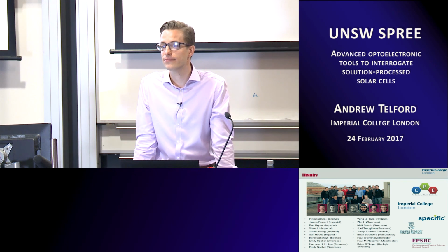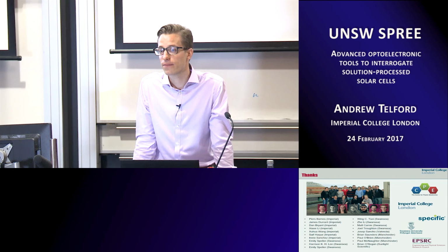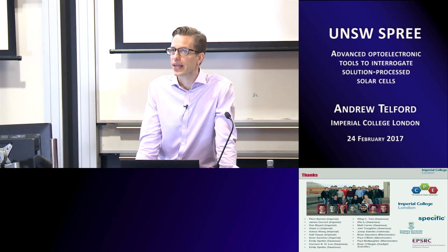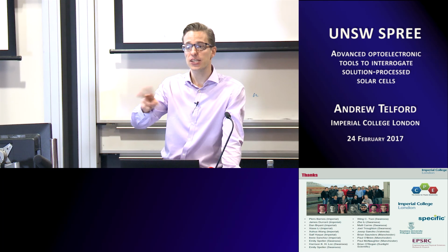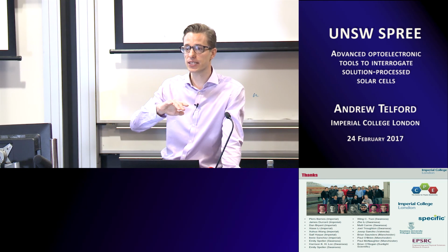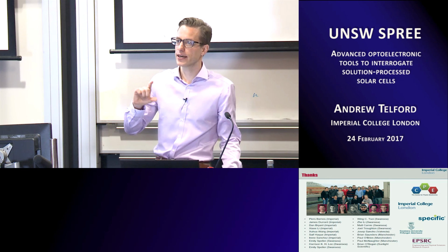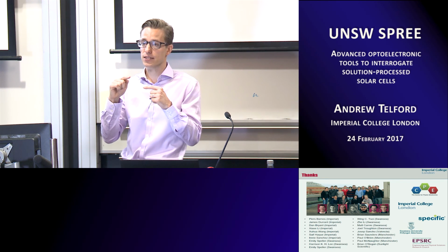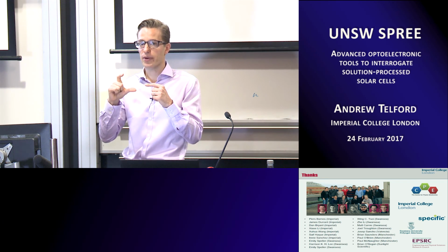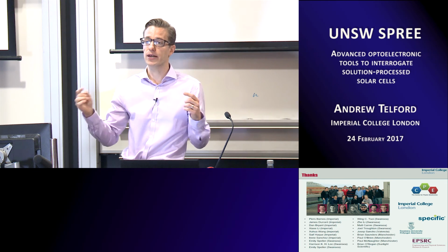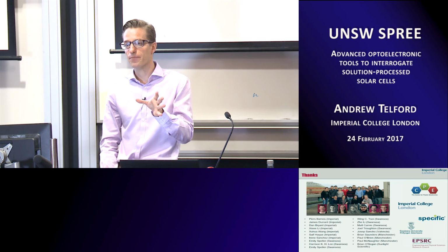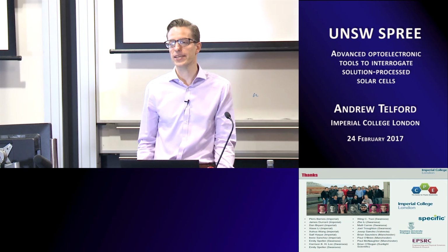You have used the EL to analyze the voltage loss. Can we use PL? The response would be similar. We actually have compared PL and EL, and I do see a similar trend. I think, though, that with electroluminescence, you're probing states that are actually electronically accessible, right? With PL, you may probe states that are optically accessible, but you can't necessarily inject electrons or holes into. So it may give you a skewed answer. But, yes, we have checked that.